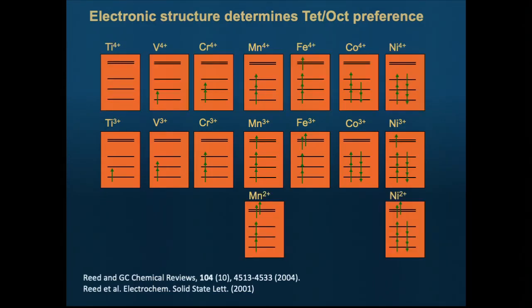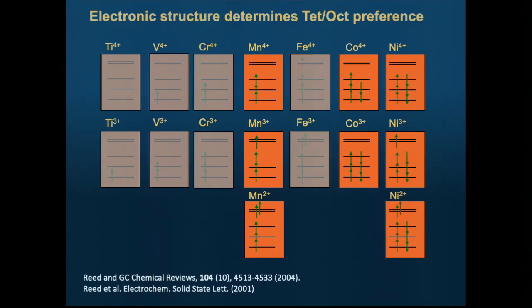So you take titanium 3+. This is not going to be a good ion, because it has only one electron in its stabilizing energy level. So titanium will migrate, and that's exactly what it does. So does vanadium and chromium. Chromium looks great, because spin polarized, it has 3 electrons. But when you oxidize it, there's only 2 left, and you don't have enough stabilization to keep it in the octahedral site. So these 2 are out. This one is out. OK, then you look at things like iron 3+. This is the worst. This has 5 spin polarized electrons, so this is largely ambivalent about its coordination. Iron 3 can do tetrahedral, iron 3 could do octahedral. This is a terrible ion to work with in a battery, because it moves all over the place. OK, so iron 3 is out, and therefore iron 4 is out as well.